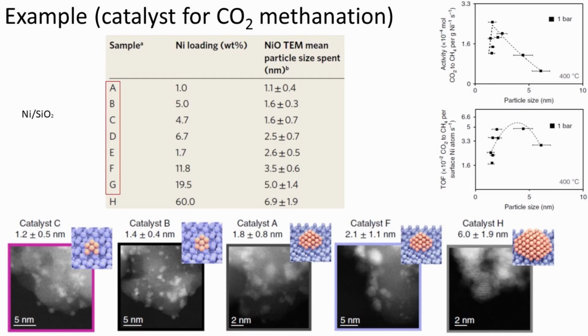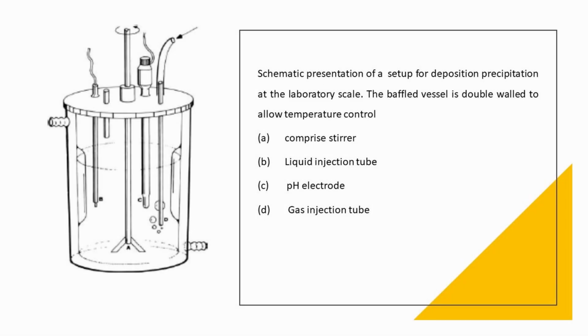In principle, this method of precipitation enables the deposition of a controlled amount of metal precursor up to high loading, and the interaction between the metal precursor and the support leads to the formation of a highly dispersed active phase after thermal treatment. In practice, the support is suspended in the solution containing the soluble precursor. The suspension is stirred, then the precipitation agent is added. After a given time of gradual and controlled addition of the precipitation agent, the solid sample is collected, washed, dried,